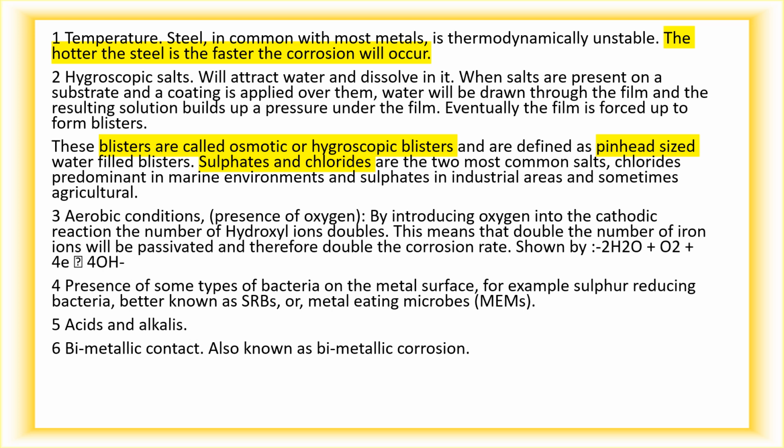Second one is hygroscopic salt, which will attract water and dissolve in it when salts are present on the substrate. So what is a substrate? The job is called the substrate in BGAS. When salts are present on this substrate and a coating is applied over them, water is drawn through the film and the resulting solution builds up a pressure under the film. Eventually the film is forced to form a blister.